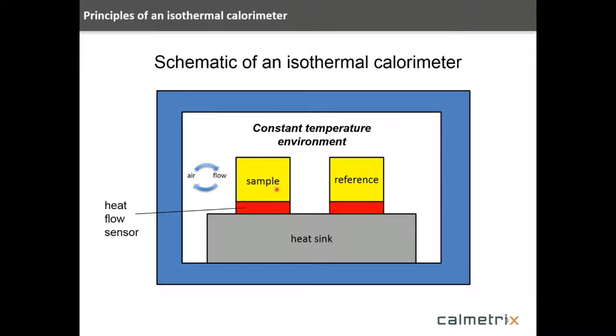So what happens when the sample goes through some type of reaction? Well, let's use the illustration of a cement cure, which is an exothermic reaction. So as that reaction takes place, the temperature starts to rise in the sample. The temperature then basically is higher than the environment. So in order for the system to come in equilibrium, heat basically flows from the sample through the heat flow sensor into the heat sink. And as that heat flows across those heat flow sensors, that's what we measure within the heat flow sensor. Actually, the raw signal coming out of those heat flow sensors is a voltage signal. And then during the manufacturing process, we calibrate that voltage to heat flow in watts. So that's the fundamental signal that comes out of the instrument, is voltage that gets converted to heat flow in watts.